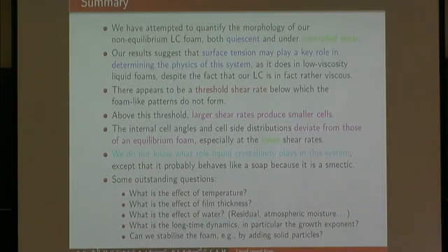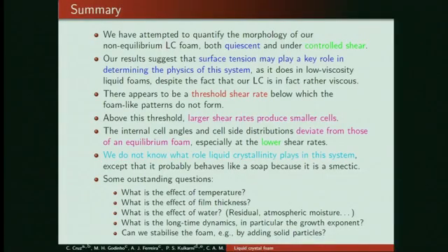Right, so this is it basically. So here are the conclusions. We have attempted to quantify the morphology of our non-equilibrium liquid crystal foams, both quiescent and under controlled shear. And our results suggest that the system, as in the case of ordinary soap foam, may be surface tension dominated, despite the fact that it is a lot more viscous than most ordinary soap foams.